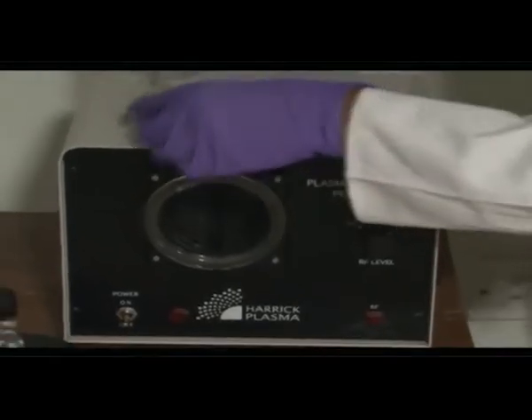So you can see the glow come. The plasma glow has come now, and you wait for about 30 seconds after this glow is there, and that ensures that your process is fully completed. This is how it actually looks like. The tube is all lighting up with the plasma, as you can see. So as this plasma process is complete, we can switch off the plasma and take out the samples.